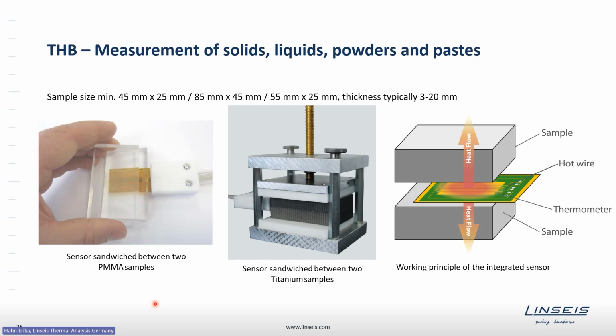The measurement principle I will explain a little bit later, but basically what belongs to sample preparation is having 2 pieces of material covering the sensor foil and fitting very precisely on top of each other so that there is no air in between the sample pieces. And to enhance the contact between sensor and sample, we typically compress this configuration using such a sample press or by putting a weight, for example, on top of that.